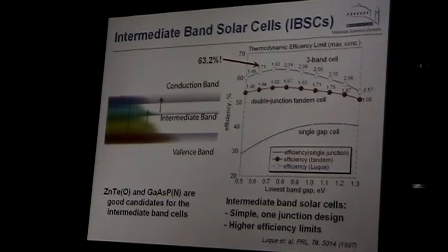The calculations show that this is really a very promising system. This shows efficiency as a function of the lowest band gap, the band gap between the intermediate band and the conduction band. The maximum is around 0.7 electron volt. So if you have this transition of 0.7 electron volt, and the whole gap from valence band to conduction band is 1.93, the rest is, of course, about 1.2 here. This configuration gives you really large efficiency, much larger than the typical tandem. And this is very promising.